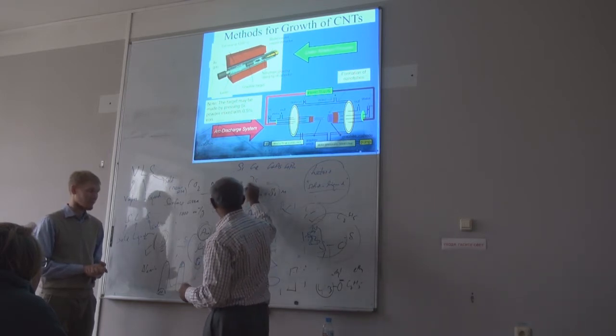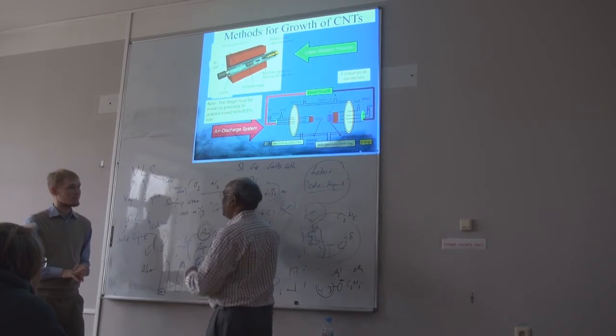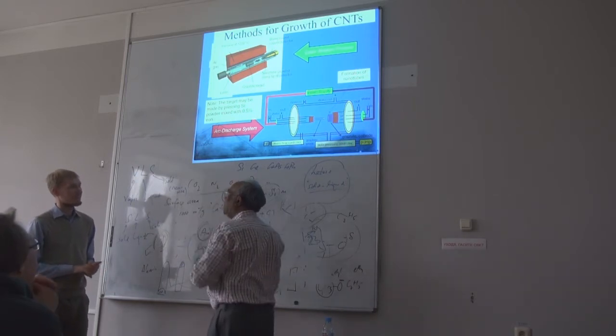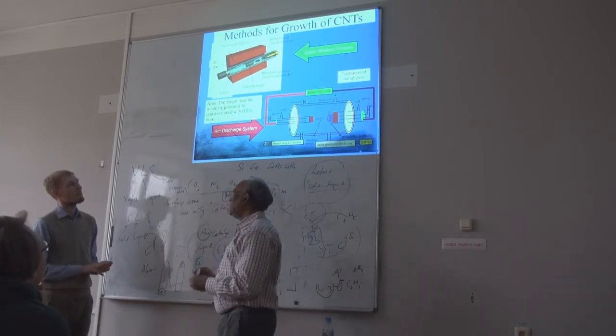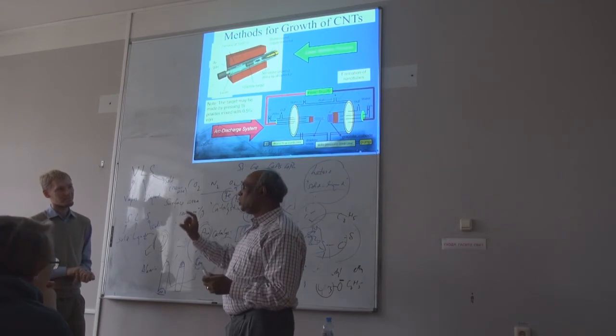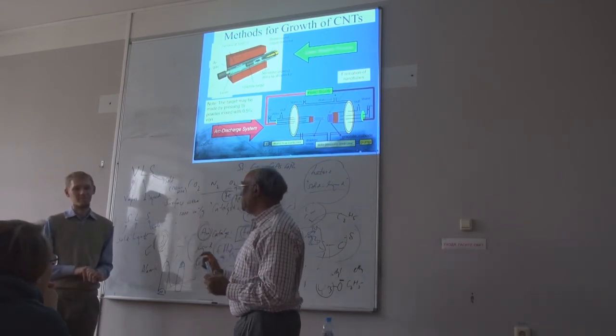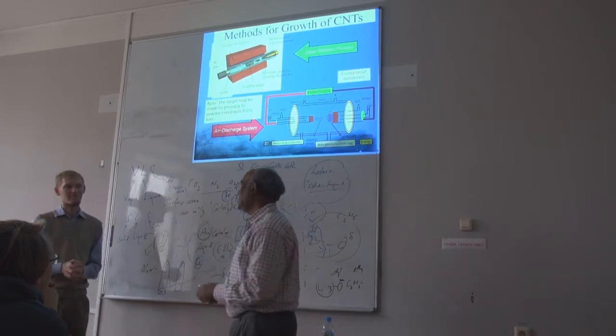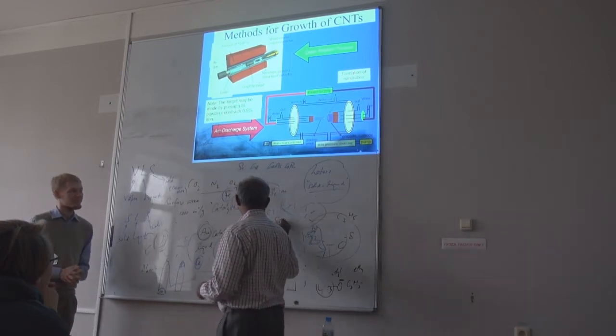But if you have water, it will prohibit this carbide formation. That will make it grow longer and become vertical. You can make something called a nanotube forest. It looks like a lot of nanotubes as a forest here. That's called super growth.